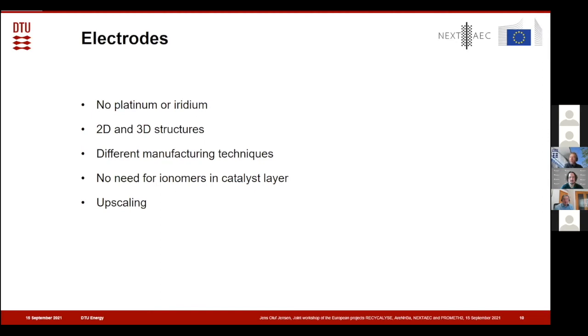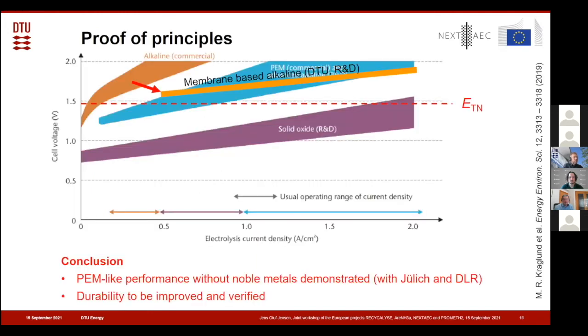When we have this concept with the ion solvating membrane, we need to have the electrolyte everywhere. So we don't need any other phases for transporting the ion. So we don't need any ionomers in the catalyst layer. That also simplifies things because that's typically what breaks down first in ion exchange membrane-based fuel cells and electrolyzers. And then we'll do some upscaling so we can demonstrate it in a larger electrolyzer towards the end. We base this on some early studies of the ion exchange membrane, and a few years ago, together with DLR and Jülich, which are also partners of the project, we published a study where we showed that with the ion exchange membrane, we can actually get PEM performance with an alkaline system.